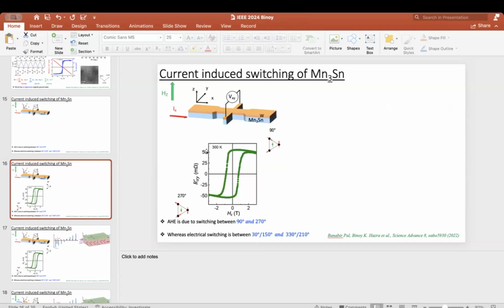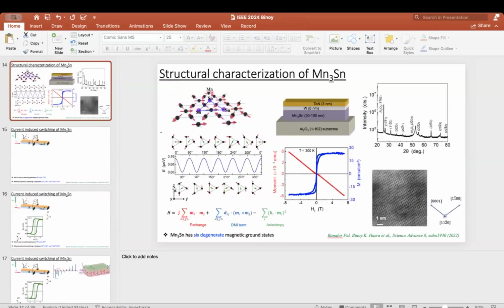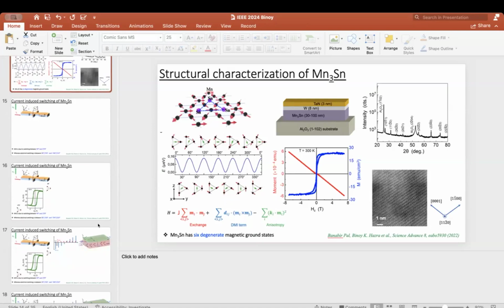So here we observe 100 milliohm, and with respect to that, in the current induced switching experiment, ideally the remaining domains are at an angle with respect to the z-axis, and if you take the projection, that will be 0.5 times m. So theoretically you can find 50% switching between the 30 to 210 domain structure or the 150 to 330 domain structure. That is what these 4 domains contribute to the current induced experiment, and we observed less switching, like 40% switching. Is it clear? Okay, he said yes, thank you.